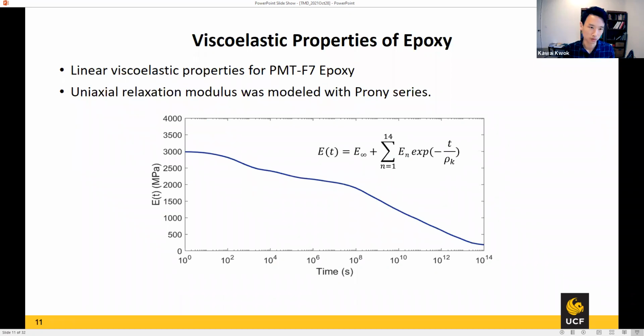This is a very fundamental thing about viscoelasticity: you can characterize materials at different temperatures, and you can form something called the master curve, which describes the modulus change over time. This is the experimental data that we obtained in the lab, for a particular epoxy that is a candidate for composite materials for that space application. You describe that relaxation modulus by something called a Prony series, so you can describe it for a very long time. Obviously we did not run this experiment for this long; it was combined from several different tests at different temperatures.